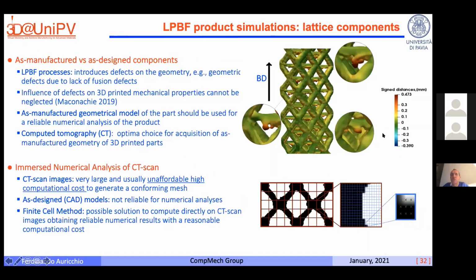One of the reasons, if you do the CT scan of your component, is that since your lattice structures are very small and you try to make them as small as possible, you get very close to the production precision, and at the end of the story, your lattice structure is extremely irregular. Here you can see CT images of our lattice structures, and you can see easily that it's completely far away from the idealized CAD component that we designed. So not only do we have very different structures, but now that we have this structure, the point is, how can we do computations with it? Because you can see that this geometry is extremely complex.